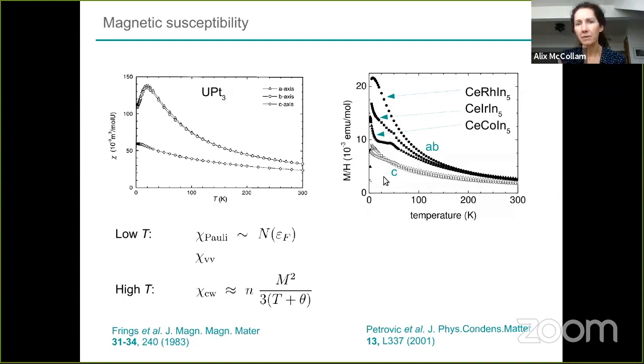And this is an example of data from the 115 family, cerium rhodium indium 5, etc. This is in the AB plane. These are tetragonal materials, and this is along the C-axis. In this case, it's hexagonal, and this one was along the AB direction, and this one was along the C-axis. And here we also have anisotropy, but you can see that there's a good Curie-Weiss behavior at high temperature, and then something else happens at low temperature, but it is large.